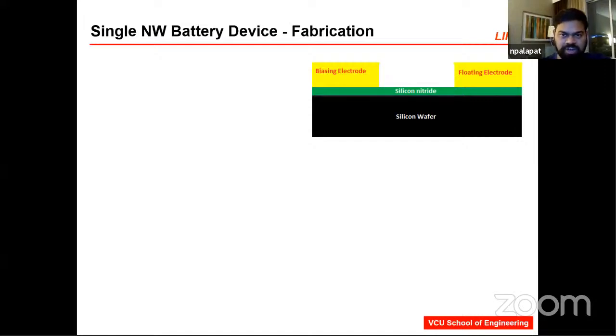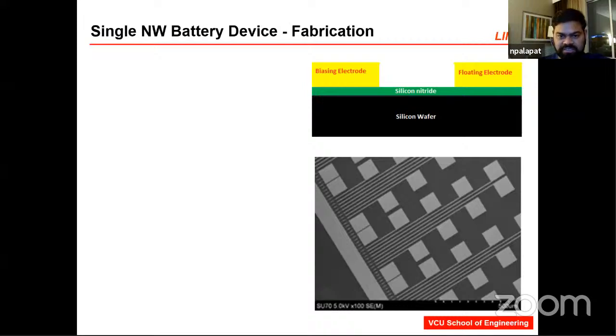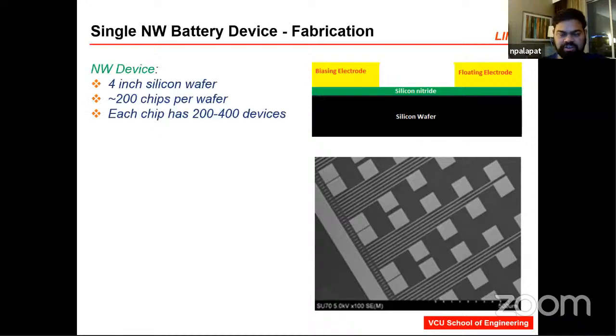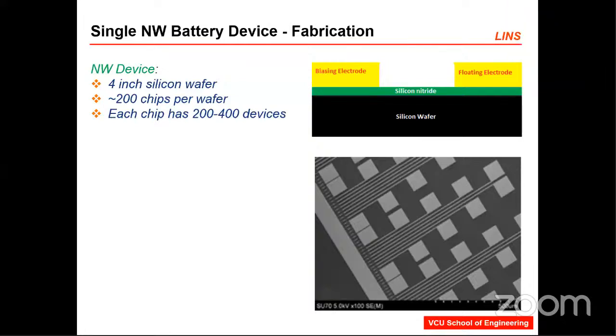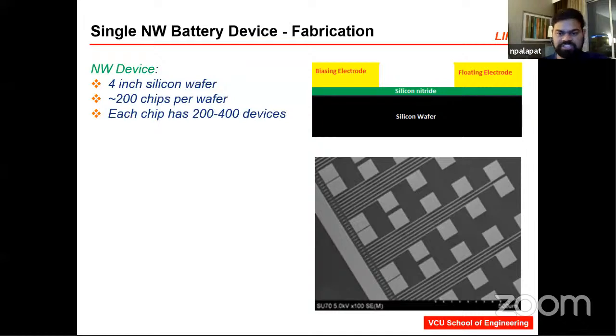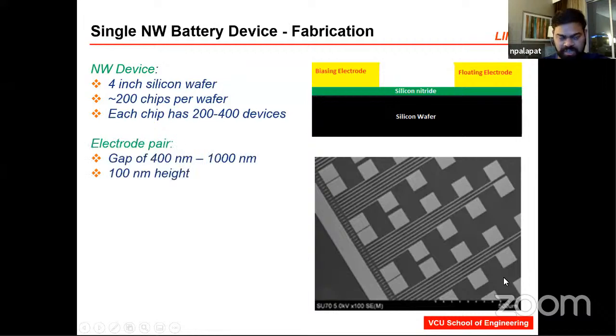So this is on a 4-inch silicon wafer. Silicon nitride is deposited initially, and the design itself looks something like this. On the left, we have a biasing electrode. It is a single pad, whereas on the right, we have these individual pads, and each of them is an individual nanoelectrode location. Each 4-inch wafer can give about 200 chips per wafer, and each chip will have this design with about 200 to 400 device locations on it. These are some more information that I just put in.